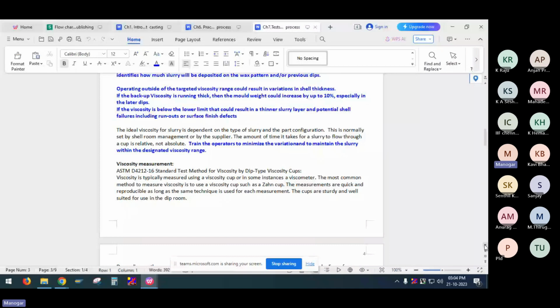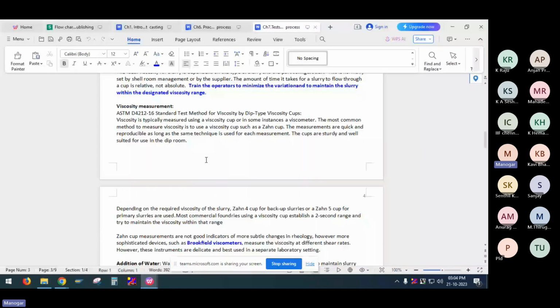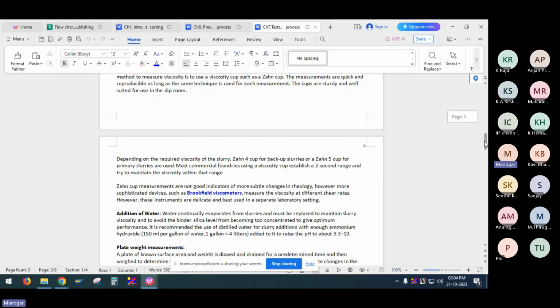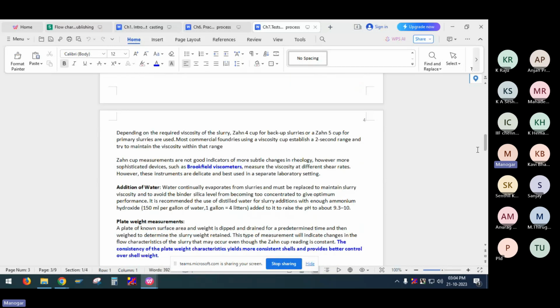So this is the standard, ASTM D4212, which suggests how the viscosity measurement test is done. People normally use viscosity Zahn cup 4 and 5. Zahn 4 is for backup and 5 for primary coating. And they use the 2 second range. And for manufacturers and laboratory purposes, people use a Brookfield viscometer, not the Zahn cup.